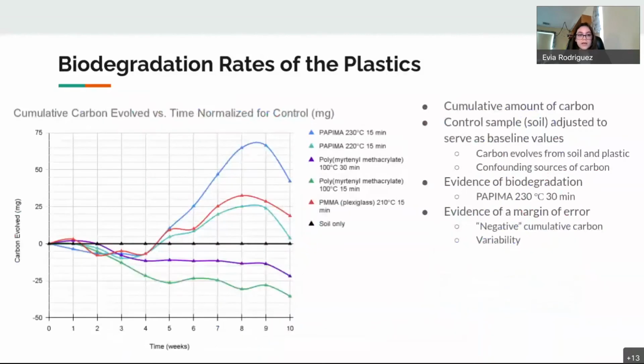After doing some calculations, I ended up with this graph, which is the total amount of carbon that evolved from each of the jars. I used the black line, which is the soil-only control sample, as my baseline for this graph, because there's a certain amount of carbon that's just going to come from the soil naturally, and then there's also a certain amount of carbon that's going to come from the plastics. So using the control as my baseline, this is the amount of carbon that comes from each plastic relative to how much just comes out of the soil baseline. So there seems to be evidence of biodegradation, especially in the light blue line, which is PAPIMA.